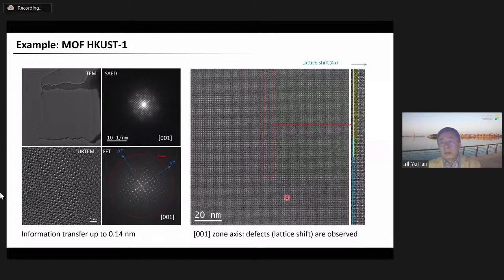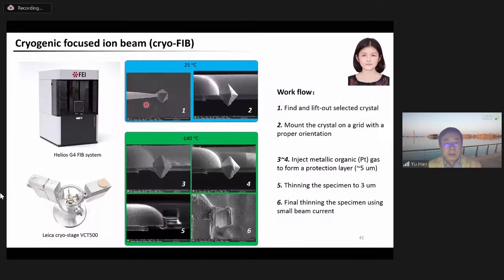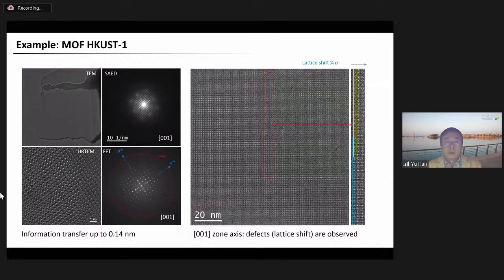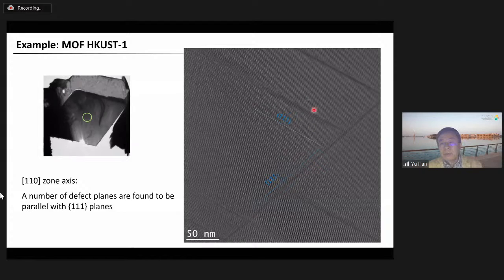So from the image, we found that there is a large amount of structural defects that exist in this seemingly perfect crystal. Yeah, the crystal looks perfect, right? But actually with cryo-FIB coupled with low dose TEM, we can see a lot of structural defects inside the crystal. You see from the 110 zone axis, we can see a lot of planar defects, and these defect planes are parallel to the 111 plane, and we will report the structure details later. And here I just want to emphasize that such structure features in large MOF crystals cannot be discovered if we don't have suitable specimen preparation and suitable imaging techniques.